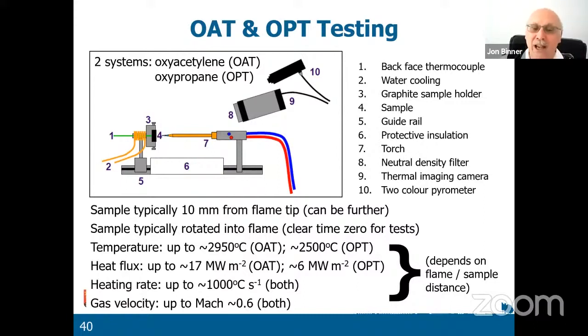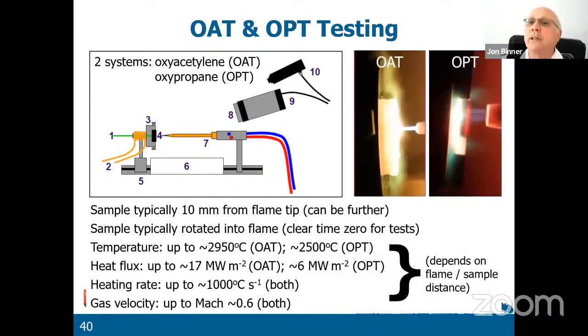The heat fluxes, the heating rates, about 1,000 degrees centigrade per second. And we've measured the gas velocity, and it's about Mach 0.6 in both cases. And there you can see the oxyacetylene torch on the left and the oxypropane torch on the right. The oxyacetylene torch, the OAT as we call it, is a single point source of energy.